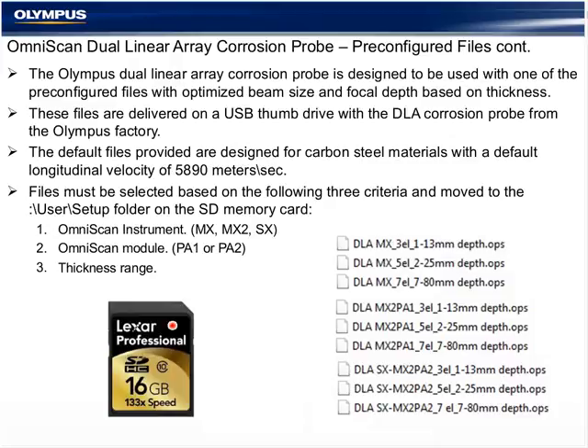The corrosion probe is designed to be used with one of these pre-configured files for optimized beam size and focal depth based on thickness. The default files provided are designed for carbon steel materials with a default velocity of 5890 meters per second. Other velocities or other types of materials are compatible with the probe and the OmniScan, and that's explained a little bit later.